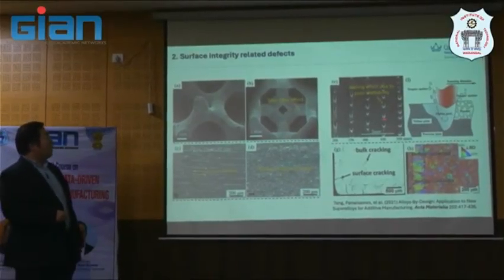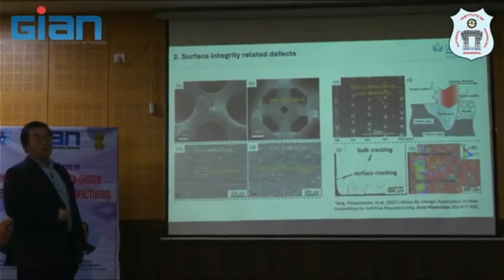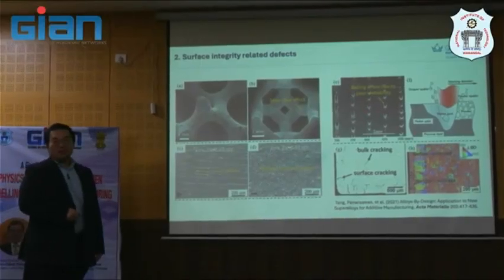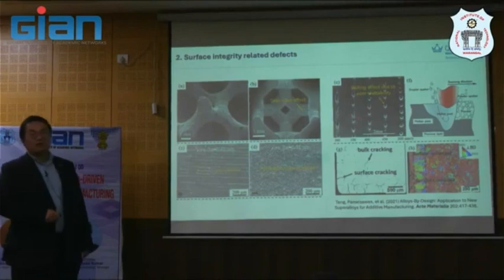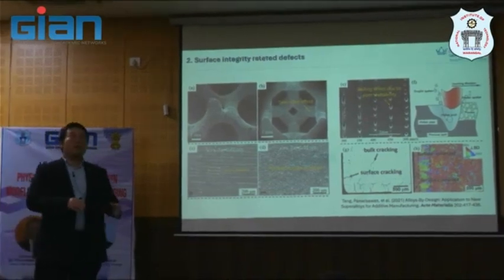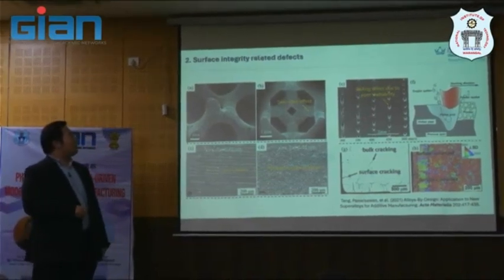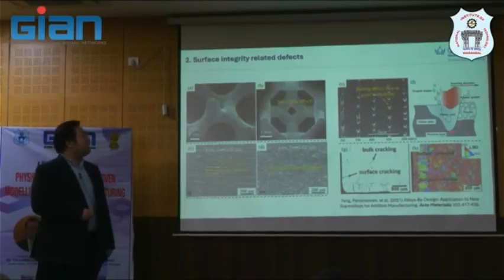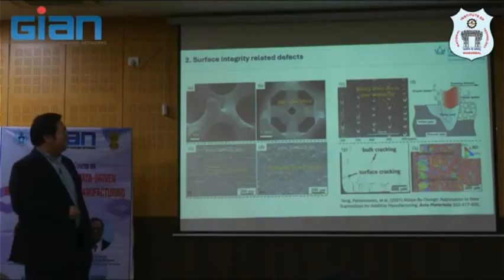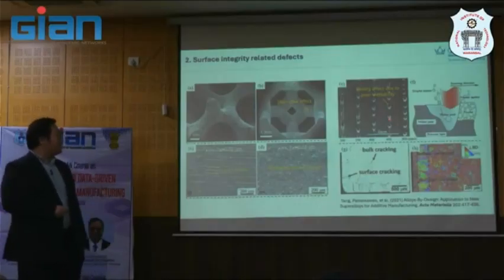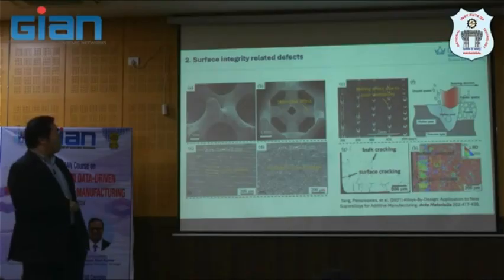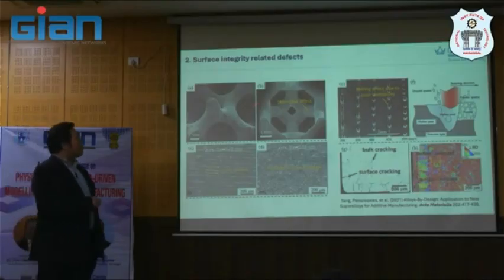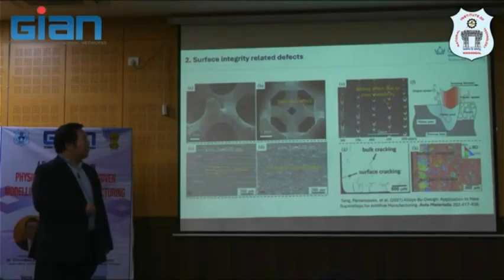And you see the balling effect is about the poor wettability, related to surface tension and probably viscosity of the metal at the liquid stage that you print. And this is to try to summarize, but it's not very inclusive like my previous diagram. And definitely this will be another challenge in terms of surface integrity. It's not just porosity, but the cracking